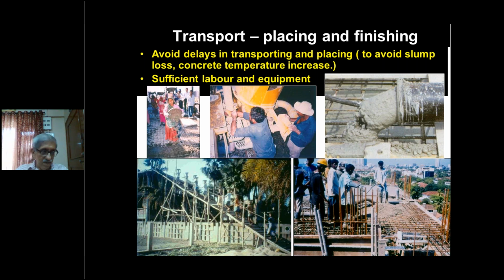It will be interesting to note that should you get a choke in the pipe due to concrete stiffening, then you go on banging the pipe, and where you get the hollow sound, you know that just before it is the plug of concrete. So you can open that plug and clean the pipe. This is because the concrete has lost its workability, proper care was not taken, and pipes were not properly protected, or there was a delay and they could not open the pipe, etc. So now they have to remove the plug.